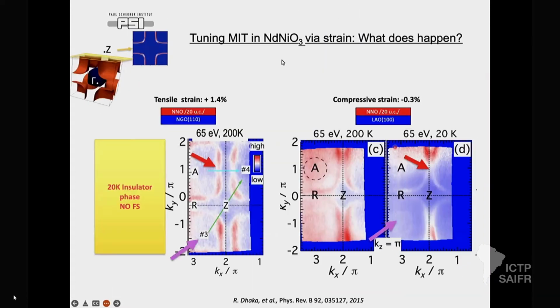A bit more on what happens when we cool down the sample. I'm now just in the AZR plane, so the Fermi surface should look like that. When we cool down, it is insulating: there is no Fermi surface to be measured at 20 Kelvin, and you can see how big this gap is. While for the LAO system at 20 Kelvin, you can still measure. The sign of the Fermi surface is still there. Of course, the spectral weight is lower, but the Fermi surface at the A point is still that round thing.